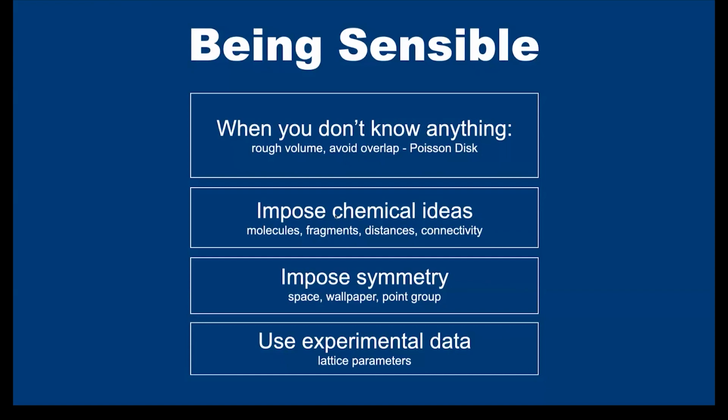structures, your sensible structures. It's also very powerful to use symmetry to accelerate the searches. Most crystal structures have at least some symmetry, and if you use symmetry operators, you shrink the configuration space. And given the potentially exponential growth in the size of the configuration space, even halving or dividing by 4 the number of atoms that you have to independently consider can make a huge difference.